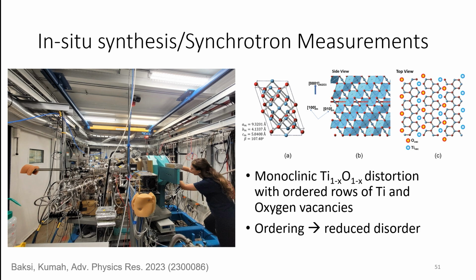All right, so we've also been doing in situ X-ray diffraction at the APS before it's shut down, and we'll hopefully be going back when the light turns on again. But here we can actually grow the materials and use the X-rays from the synchrotron X-ray source to measure the samples during the growth. And we've applied this to measure the sample I showed you where you have a metallic to superconducting transition. And what we found here is that this material has a 1-to-1 ratio of titanium and oxygen, but there are vacancies of titanium and oxygen in the system where you have these ordered rows of these blue titanium vacancies and oxygen vacancies in the system.